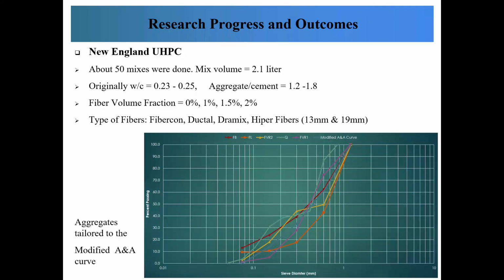So far, we have mixed about 50 UHPC mixes at a volume of 2.1 liter each. The water-to-cement ratio is usually in the range between 0.23 and 0.25, and the aggregate-to-cement ratio was investigated from 1.2 to 1.8. Aggregate particle distribution was tailored to follow the modified Andreasen and Andersen curve. In terms of fiber reinforcement, we started to add fibers in the volume fraction of 1, 1.5, and 2%, and use different types of fibers available in the US.